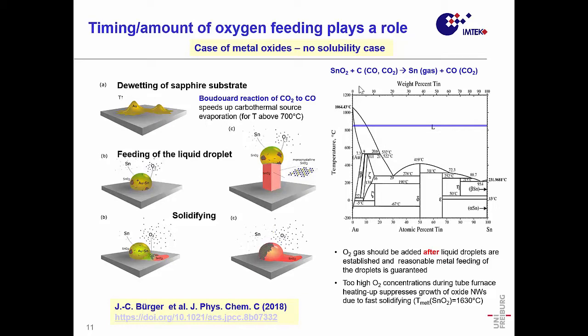oxide into these structures? Because if you have the oxide, it immediately solidifies because it has no phase diagram. And what you end up with is kind of like water with ice flakes. It's the same thing, and if you have too much oxide, you actually cover the whole cap, and then the growth of the nanowire stops. So you have to control that in a good way. You have to decide at which time to put the oxide in, and that also means leakage control, because oxide could also get into your system due to leakage.